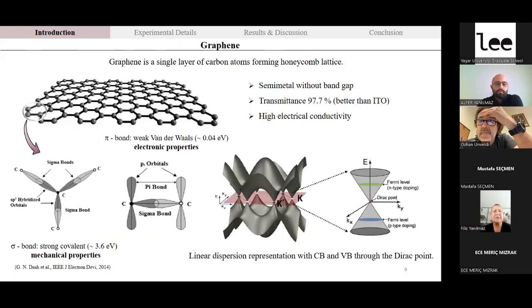To continue with the graphene, as we know, graphene is a single layer of carbon atoms forming a honeycomb lattice. This graphene material is known as a semi-metal without a band gap, and it has high transmittance when compared with the indium tin oxide material, and graphene has high electrical conductivity.